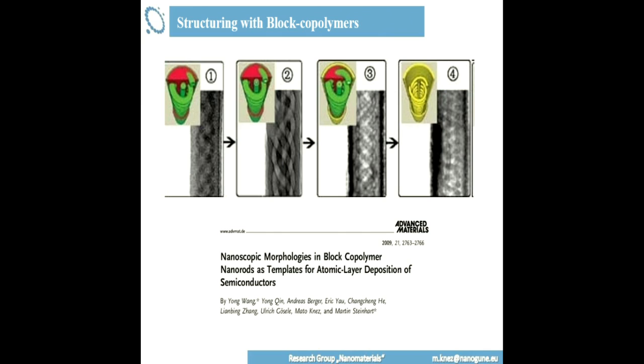For example, if you have diblock copolymers, which you then infiltrate. This is some of our very old works where we did diblock copolymeric structures inside of porous alumina. So it's two polymers, helical structures. And then if you do zinc oxide infiltration, you can basically deposit a coating on the interface between those two polymers. Then if you remove the whole template, you will end up with some structures, which are helical in this case, zinc oxide. So it's a very nice way to do some structuring.